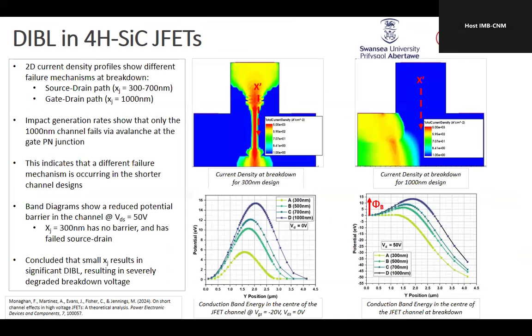And my student Finn did a lot of good work on this. Okay, and what we noticed is that, as I mentioned, the larger channel lengths were about 1,000, and the lowest was about 300. And what you can see here are 2D plots of the current densities at the onset of breakdown. This left-hand side one is for a very low channel length, like 300 nanometers. And this right-hand one is for a maximum channel length, okay? And what we noticed is that this one was breaking down in the channel region, right? Because the channel region for a JFET is in the middle of the pillar, right? Whereas the right-hand one, this is what you want, was breaking down at one of the edges, okay?